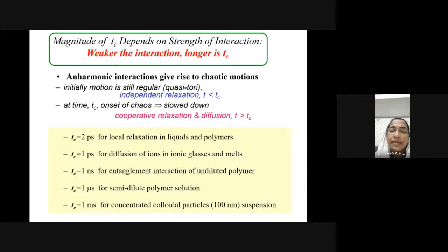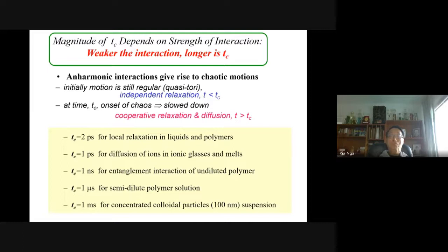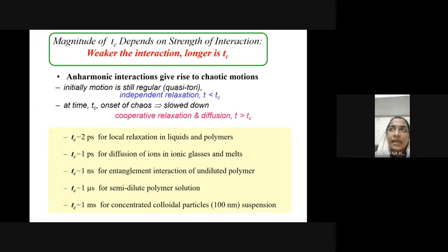But when I replaced sodium with one bulky cation, the dielectric behavior again arose. The JG relaxation of ibuprofen is still there, but it shows some shift in the time scale and temperature scale, and the behavior is also changing. That's why I asked whether it has a dependence on the size.